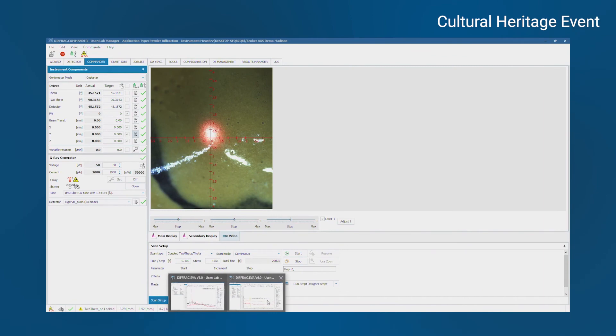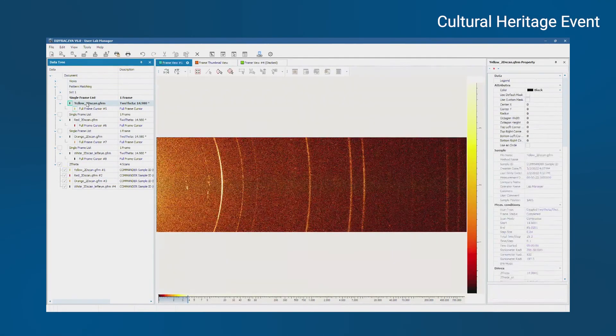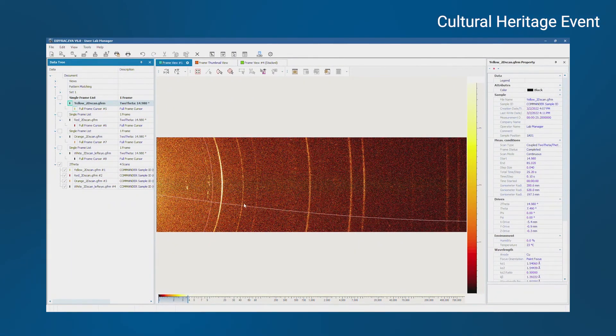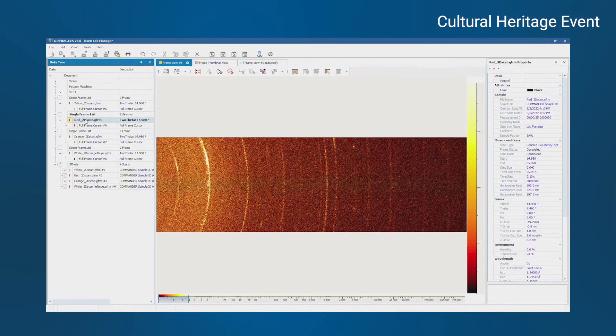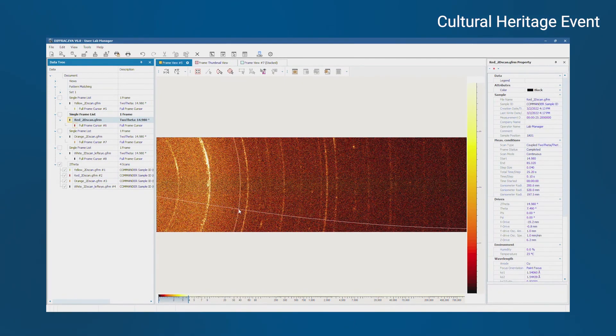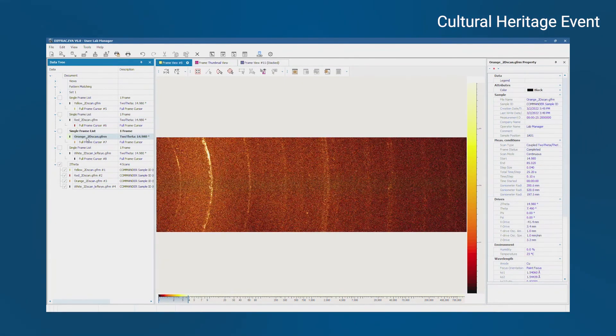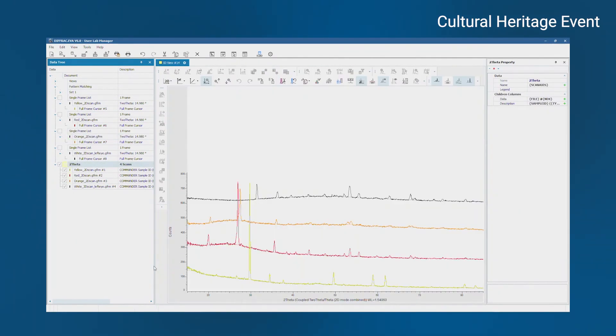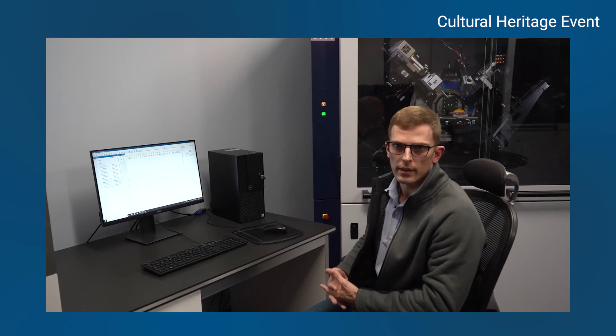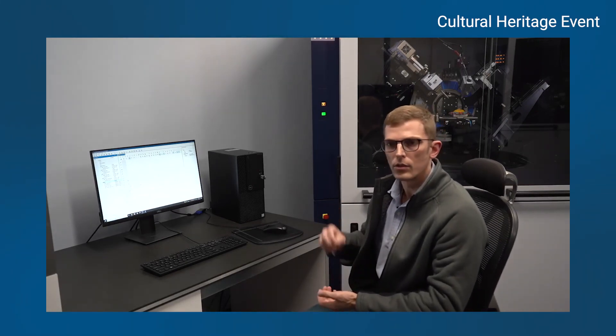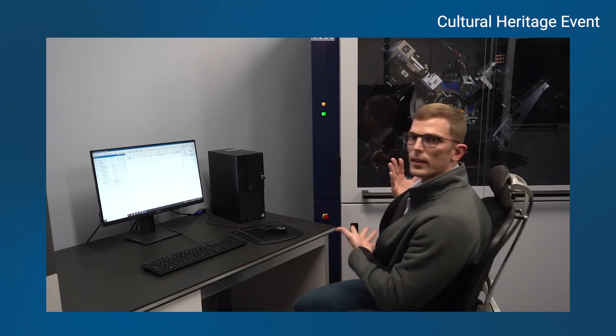And just to show you what it looks like, I've already done this as well. Here's an example for the nose region, you can see the 2D pattern looks like this. Some very sharp peaks. Then if I look at the red lips, clearly we have diffraction rings in different places. Or if I check one of the orange regions around the outside, it's different again. So just showing the overlay of the integrated data, we could see each pigment has different crystallites, different crystal phases present, which you can just find instantly by targeting those regions using an instrument like this.